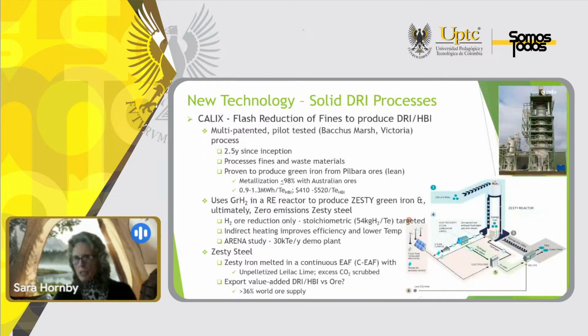The solid DRI process, Calix, I mentioned earlier, it's a flash reduction of fines down a vertical tube. It's multi-patented and it's been pilot tested in Bacchus Marsh in Victoria, Australia. They've developed this in 2.5 years, which is amazing, and they can process fines and waste materials. It's been proven to be able to produce green iron from the Pilbara ores up to 98% metallization, although some of the really bad ores are only down at 70-odd%.